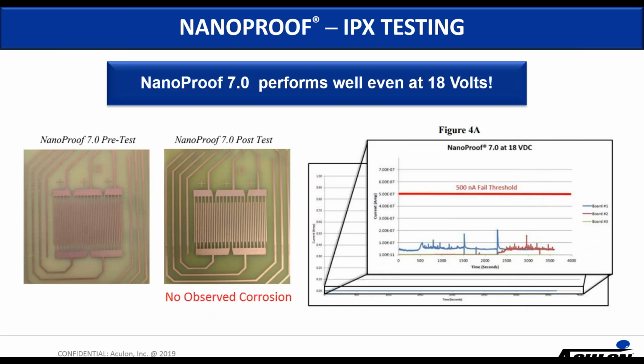Now, here's an example of after 18 volts in salt water for 60 minutes, NANOPROOF-7 before and after test. There's no observed corrosion, and you can see the data. There's three data sets here. They all fall well below the 500 nanoamp threshold.